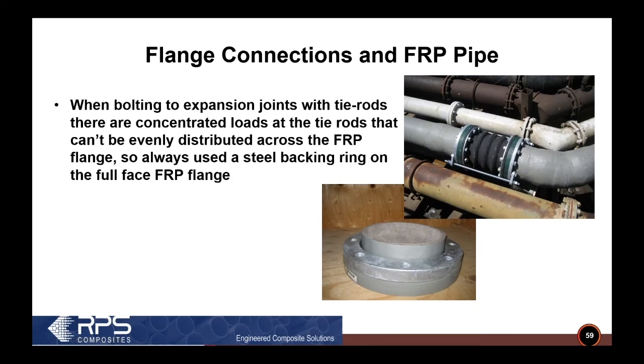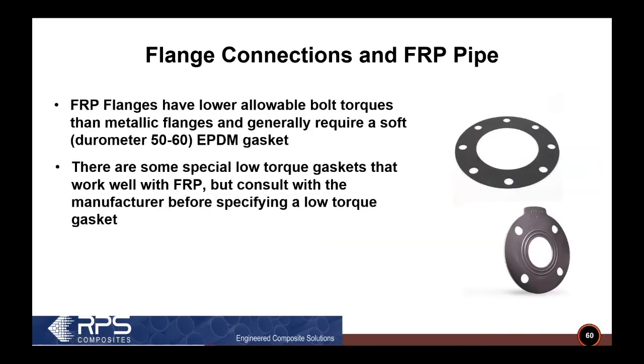So when the pressure thrust comes onto the expansion joint, now all the load is transferred to two tie rods in this case, and you'd have a concentrated load on the FRP flange, which is generally, again, not a ductile material. So you'd want to distribute that load by sliding a steel backing ring behind the FRP flange. The load comes on to the tie rods. It pulls that backing ring more evenly onto the backside of the FRP flange. So that's the preferred way to connect to an expansion joint.